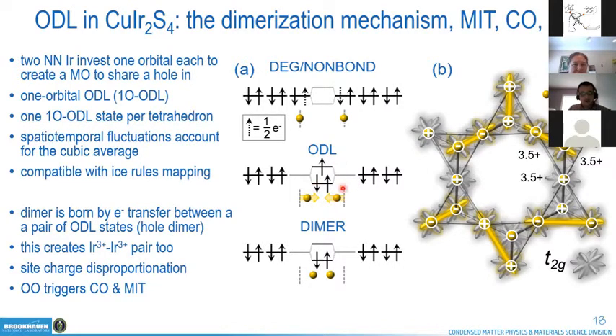So in this picture the transition necessarily involves a transfer of charge, a charge disproportionation, and this process would be responsible for generating 3+ and 4+ species, which are behind the charge ordering, and then ultimately orbital order triggers the metal insulator transition. Okay, so that would be the scenario in this picture.